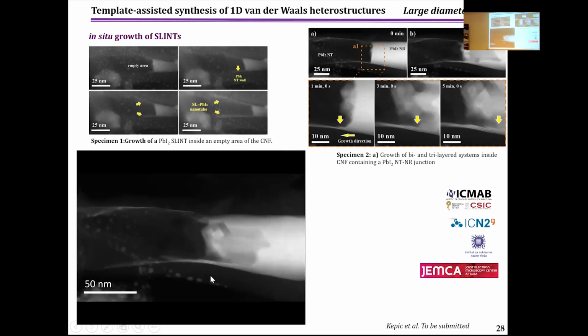So here we can see how the system evolves along time. One thing is that this way we can control the time in which this process occurs. And also this process is dependent on the temperature of the system. When we perform treatments at low temperature, these changes occur at a lower rate.